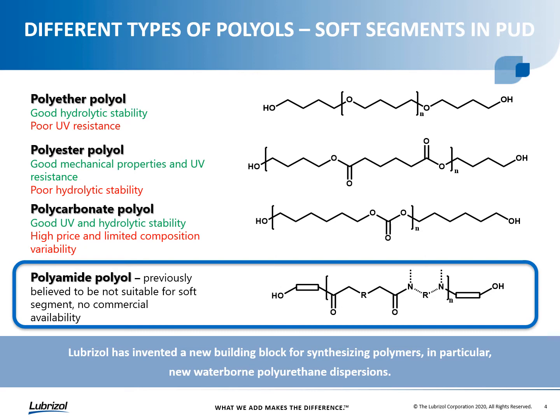so they're higher in performance, but they tend to also be higher in price, and there's just not as many of them to choose from. There's limited composition variability. And then we have the polyamide polyol, which was previously believed to not be suitable for use as a soft segment, and there was no commercial availability. But Lubrizol has invented a new building block for synthesizing polymers, in particular new waterborne polyurethane dispersions based on these polyamide polyols.